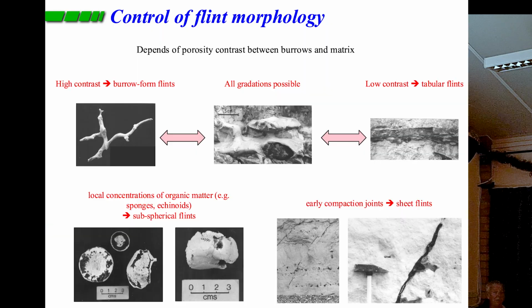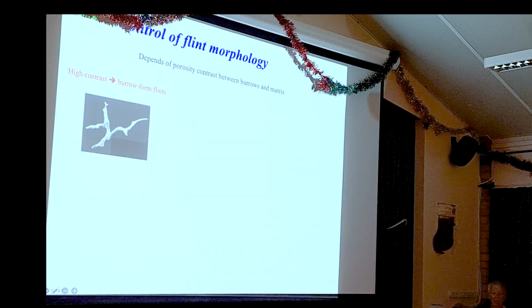What controls the shape? Well, for the normal bedded flints, the shape will be controlled by whatever pathways the oxygen diffusing down and the H2S diffusing up became to be mixed. If you've got a burrow, normally the burrow infill is less compacted than the surrounding sediment. The mixing would occur within the burrow. This particular sample is reflected in the crustacean burrow. The whole burrow is about so big. And so we get a burrow-form flint.